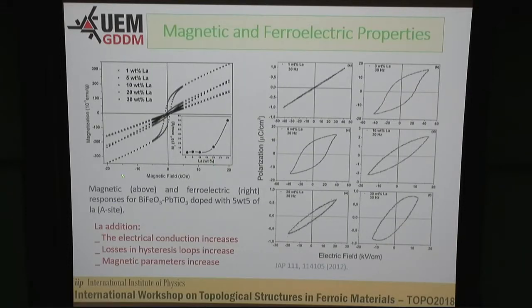This material, as I told you, has a magnetic response that increases with lanthanum addition, and also a ferroelectric response that is better for 3% and 5% of lanthanum in this structure. When this concentration grows, the leakage current prevents the correct characterization of the ferroelectric response.